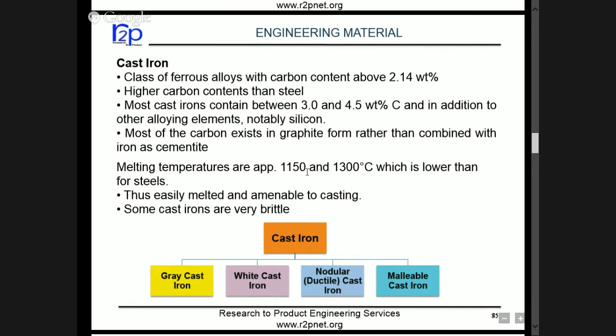And melting temperatures are quite low, 1150 to 1300 degrees centigrade. So the heating expenses are low in the case of cast iron. Like in steel, you have to go to 1450, 1500. Here the temperatures are low, thus it is easily melted and amenable to casting. The popular cast iron grades are one, the grey cast iron, and the other, the nodular or SG iron, which you know by the other name. They are the popular grades. White cast iron or chilled cast iron is also popular in the case of camshafts.